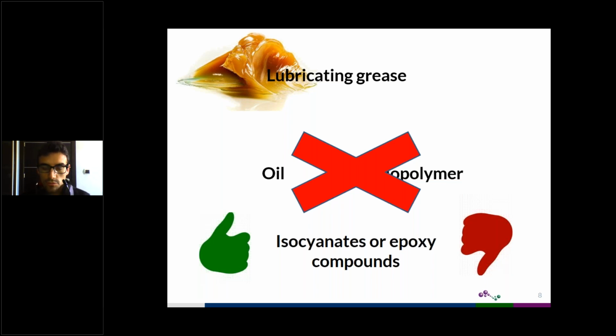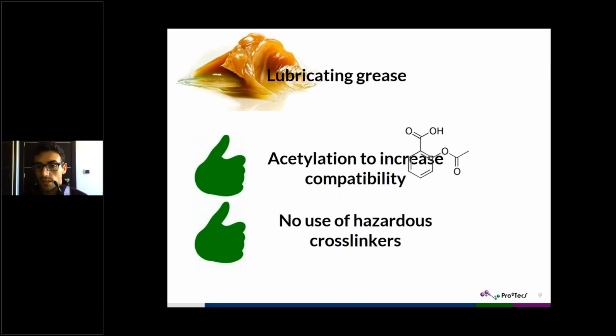And for that, we focus on the modification of the biopolymer. And that modification of the biopolymer we did by acetylation. With the acetylation, we increase the compatibility between the oil and the acetylated lignin. Why? Because now they are more hydrophobic, both of them, so they can compatibilize better. And moreover, we eliminate the use of hazardous cross-linkers. So in this system, everything is completely renewable, and we can create systems that are harmless to the environment.